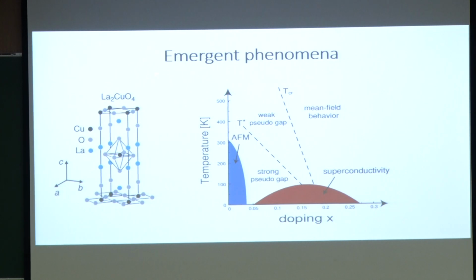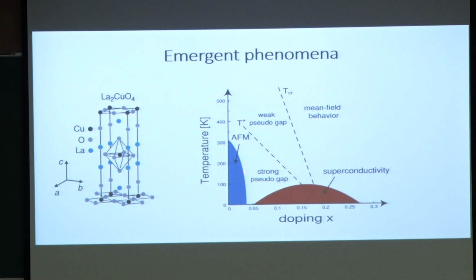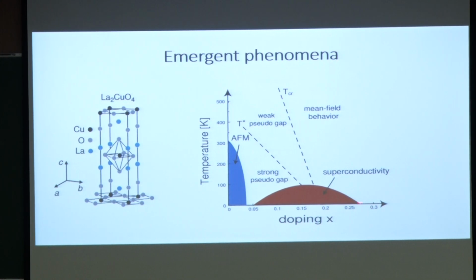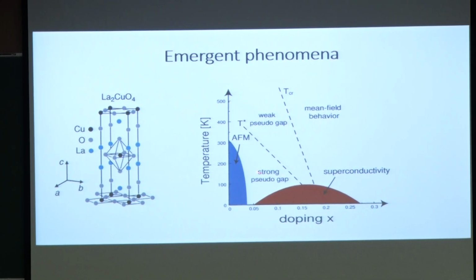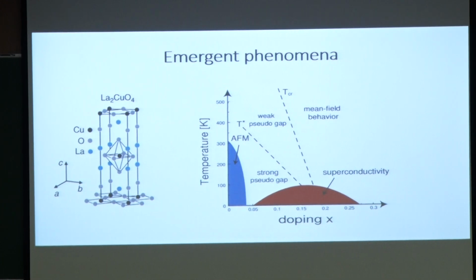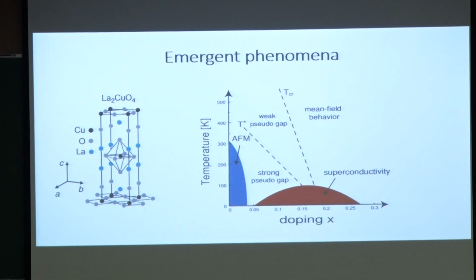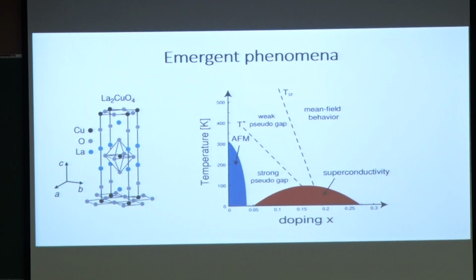In the half filling case, you have an insulating ground state, but if you dope it with holes, which means that at some of the sites you make the orbital completely empty, then the electron can hop onto that empty site. And if you do that, then you induce metallic behavior into the system. The magnetic ordering, which was because of superexchange or the virtual hopping, starts decreasing, and you start seeing a very interesting phase, which is superconductivity at low temperatures. Besides the superconducting phase, you also see a plethora of emerging phases in these kinds of systems. So this was just an example to motivate you that emergent physics happens in these materials.